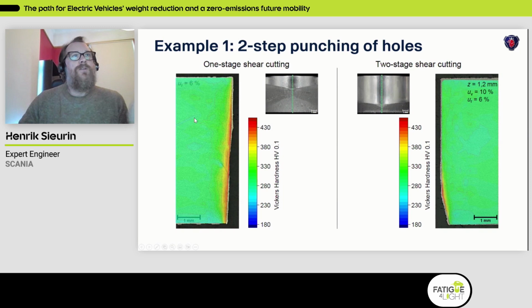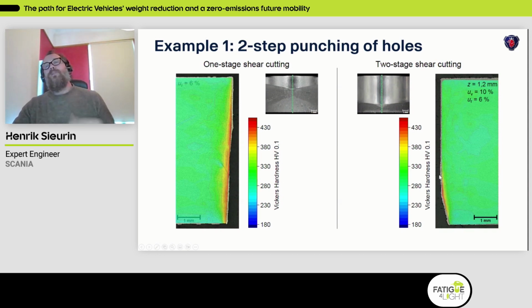So to the left, you see a typical one-stage punched hole with the shearing zone and the fracture zone. You see quite high hardness in combination with the poor roughness, which is not good for fatigue. In the two-stage cutting or punching, on the other hand, you can compare this blank zone, this shearing zone. It's much longer. You have no residual stresses, and you just have a small fracture zone.